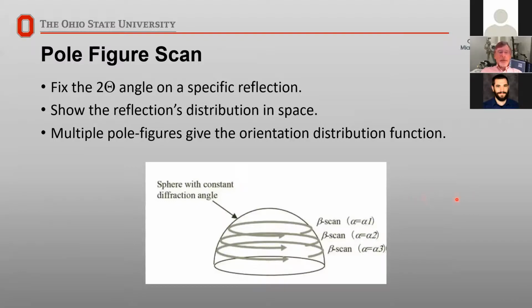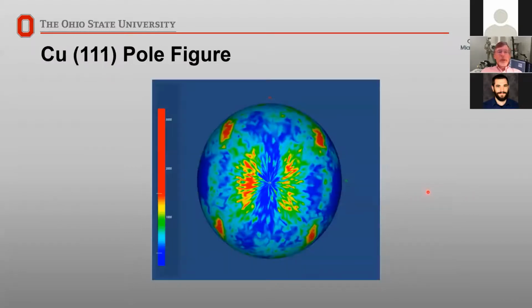And what you get for a single pole looks something like this. So this is some rolled copper foil, and this is the 111 plane in the crystal. So this would be the body diagonal going through the cube. And these red parts are where most of the 111 planes are pointing. Now, the rolling direction is vertical. So this tape was aligned more or less up and down with my scan.